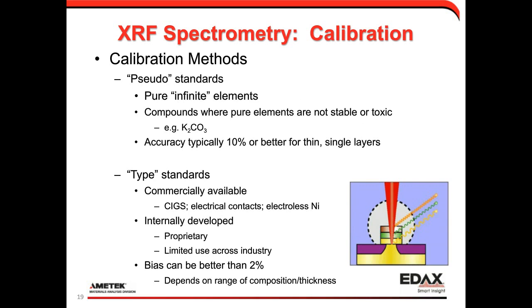What I wanted to do was comment a little bit about, well, what do I mean by standards? So there is an application note in the resource list that gives you a more detailed description and then some examples of what we've done in calibrating. But it can be something as simple as what I call using pseudo-standards. So they're not real standards at all in the sense that many people think of this, but it could just be pure infinite elements. So let's say that I want to measure a nickel coating. Well, I can calibrate measuring that by measuring a bulk, infinitely thick piece of nickel.